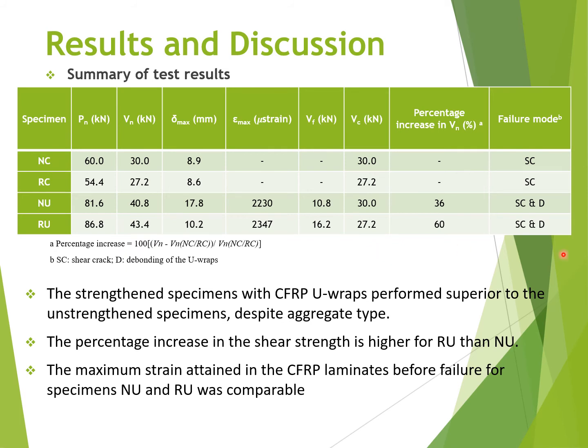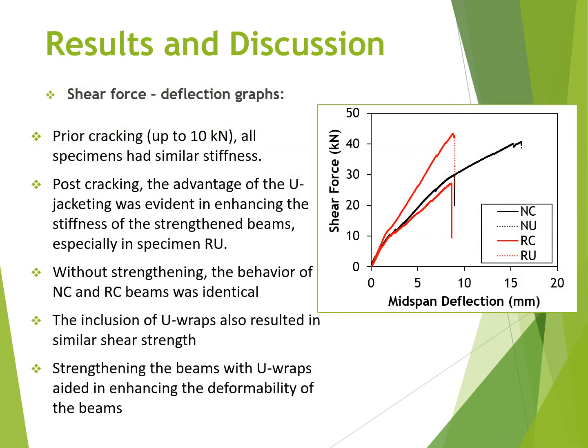You can see here that the strengthened specimens with CFRP U-wraps, NU and RU, perform superior to the unstrengthened beam despite the aggregate type. The percentage increase in the shear strength is higher in RU compared to NU, with a 60% increase in specimen RU and 36% increase in specimen NU. The maximum strain attained in CFRP laminate before failure for both the U-wrapped specimens were comparable, as both specimens attained very close load capacities.